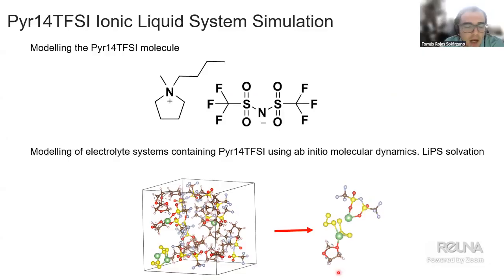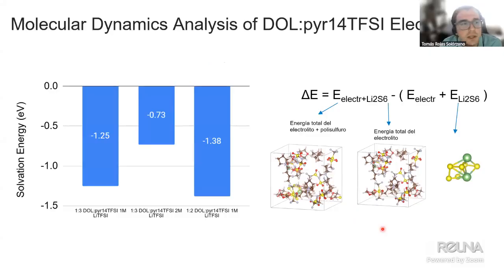And then we can observe how the ionic liquid reacts with the rest of the electrolyte. And we can calculate, similar to what we did before with the binding energy, this time called the solvation energy. So we run the cell completely, meaning the complete electrolyte, including the ionic liquid, and we also add the polysulfide. Polysulfides are these compounds that form in lithium sulfur batteries as part of their cycling. And ideally, they will take the lithium and place it from one side to the other of the cell.